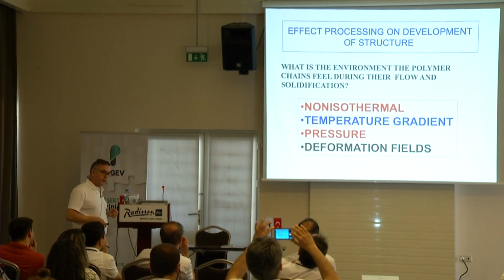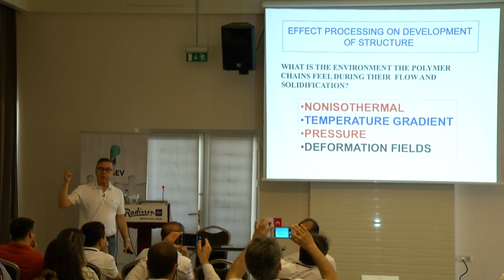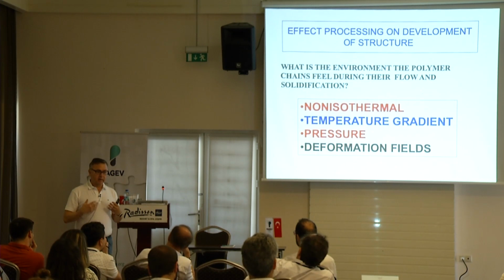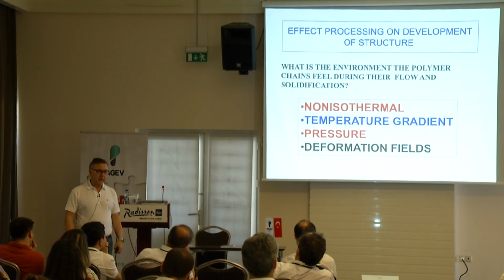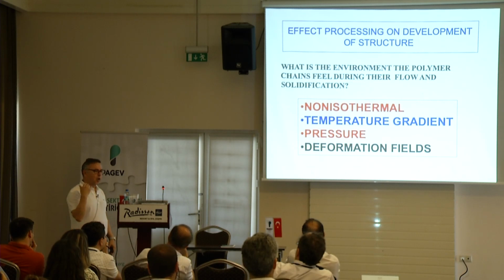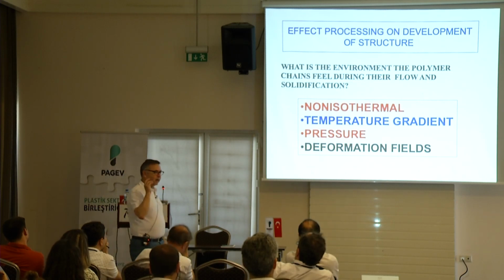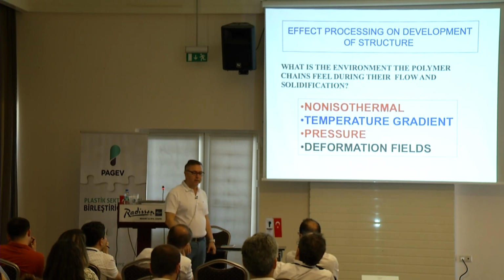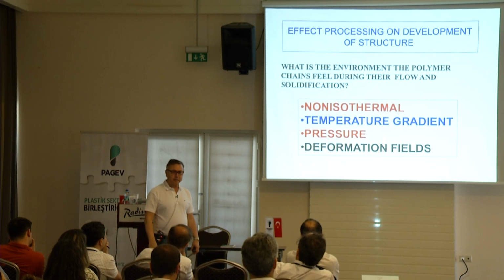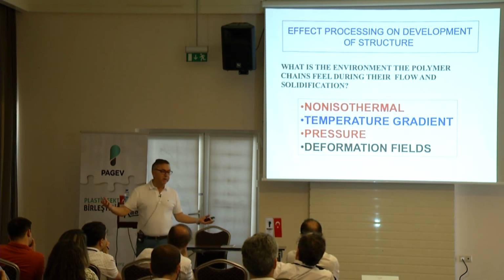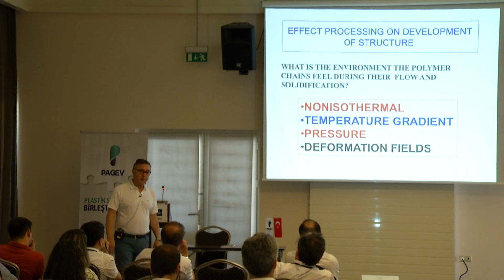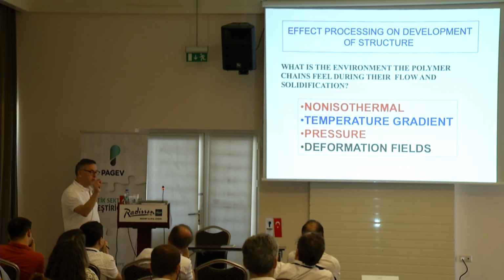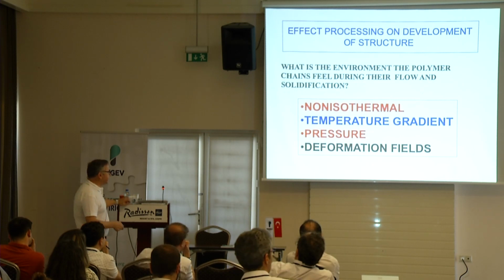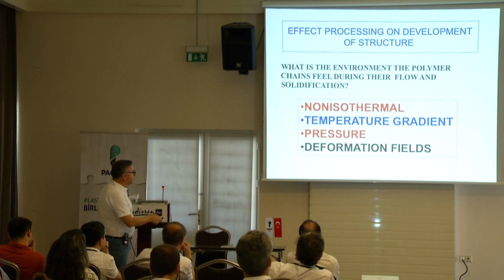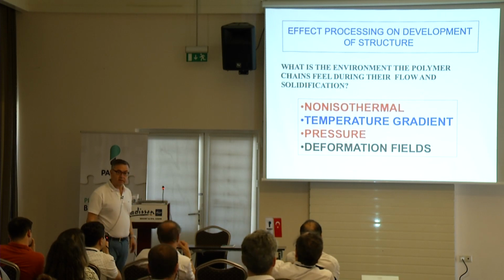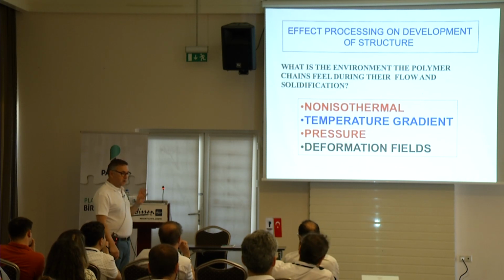So they're non-isothermal. And one of the most important properties of the polymers is that their thermal conductivity is very poor. When you have a very poor thermal conductivity, the opening of the mold takes time. That's why Jakub told you can take out the nylon at 130. I can't believe it, actually. Really? Wow. 130 degrees. Well, it's still 100 degrees below the melting point, so it's perfectly OK for the material. But 130 degrees, that's pretty hot. Yeah, you can burn your fingers. Temperature gradient. As a result of that, because you have a low thermal conductivity, you have sharp temperature gradients. That's a given. And sharp temperature gradients are important.